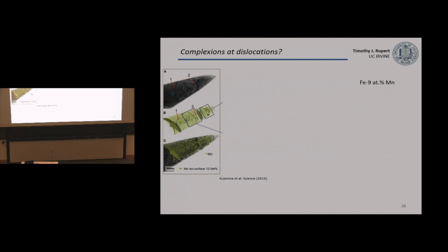They do this really beautiful materials characterization. They make these thin little needles of material. They can do transmission electron microscopy and pick out all the defects. And then they can take this thing and do what's called atom probe tomography, where they rip all the atoms off and find their chemical composition. And they can correlate these things.